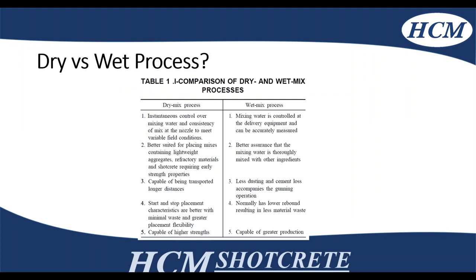Comparing the two different processes: with dry mix, you have the functionality to change and control the consistency of the mix in the field based on conditions. It's better suited for tight-on-space areas needing high early strength properties, similar to rehabbing a bridge where you need high strength if there's vibration from vehicles. It can also be transported over longer distances because you're not adding water until the nozzle — you're not under a strict two-hour timeline. Additionally, for smaller quantities, start and stop placements are better; you have less waste and don't have to pump down your lines.